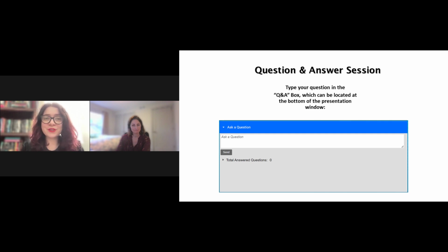Great, thank you. And our next question for you is how are the other attributes, not viscosity, listed on the certificate of analysis affected by storage and storage conditions? Yeah. So I talked about BHT, which can evolve over time, and our data suggests that this process is really slow, much slower than the viscosity loss rate at a given storage condition. So we've seen batches go out of viscosity spec, and the BHT content has moved a little bit but is still well within the specification and fairly close to the starting BHT value. It takes a long time for that BHT to sublime off.